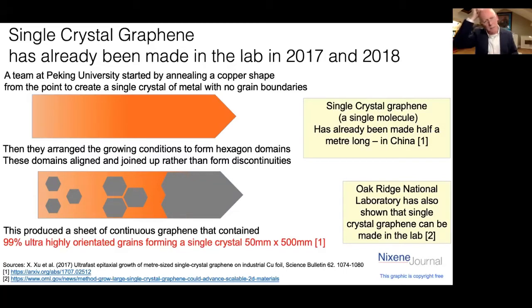This is work that's been done by Peking University in China. The way that they did it was, do you remember I showed you that piece of metal foil with the crazy paving? They got rid of that crazy paving by annealing the copper underneath to create a single crystal of metal. And then they grew the graphene on that. But cleverly, they arranged these hexagonal domains of graphene so they all aligned. So when the domains grew together, they connected and locked together to create this single crystal, a single molecule. They made a single molecule of graphene which was 50 mm by 500 mm. Quite surprising, staggering. And you can see that once the process optimization guys get onto this, scaling up is actually quite doable.